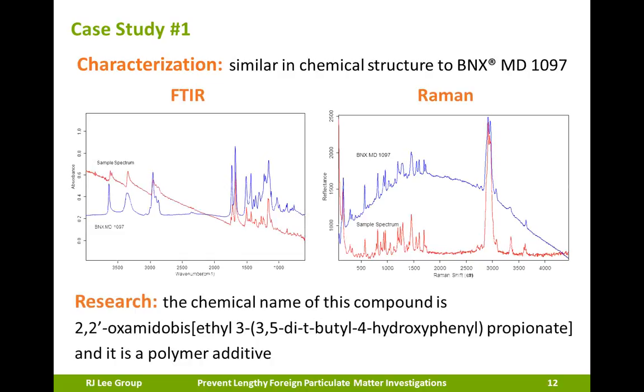As you can see, the red spectra in both the FTIR and Raman results is representative of the sample, so the needle-like particles, where the blue spectra were obtained from the standard reference material. It doesn't take an expert to look at those results and conclude that they were nearly identical. The next step was to further investigate this material. We did some research on the BNX material and obtained the chemical name of the compound, and we also confirmed that it's commonly used as a polymer additive.